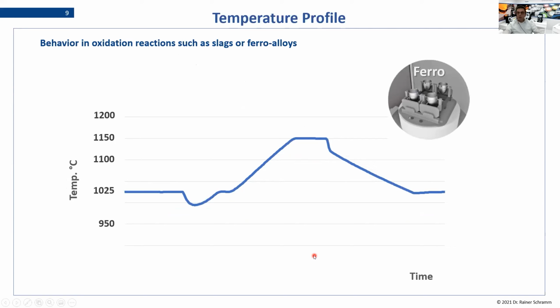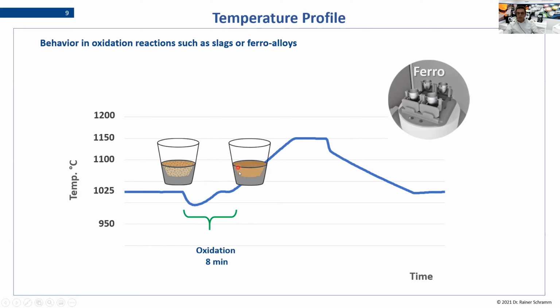Another special application would be something like ferroalloys or slags, where you need an oxidation step before. So let us assume we will do something like ferrochromium. Then we would mix our ferrochromium with, for example, strontium nitrate. We make an oxidation mixture. We put it in a kind of a dumped flux bath, and then at a temperature of 1025 degrees, for example, we will make an oxidation for 8 minutes. Over the furnace window, you can observe this so you know when this is finished for your application development. And after this is done, there will be already a melt where all the ferrochromium is now oxidic, iron oxide, chromium oxide. The flux is still solid.